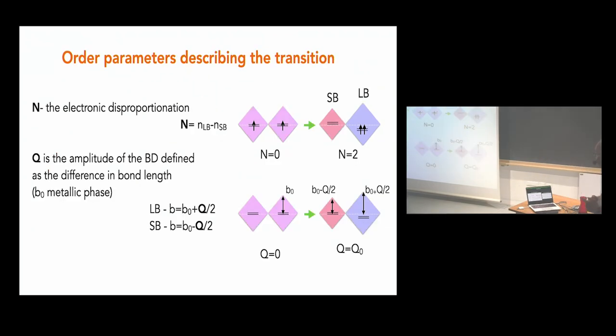To describe the transition, we can use two order parameters, and this will be useful later. The first one is n, the electronic disproportionation, and this is simply the difference in number of electrons on the long bond minus the short bond. So this is the metallic state, 1, 1, so n equals 0, and in the extreme case, in the insulating state, n would be 2. The other order parameter you can use is Q, which is the amplitude of the breathing mode, if you want, defined as the difference in bond lengths. So this Q is also 0 in the metallic phase and finite in the insulating phase.